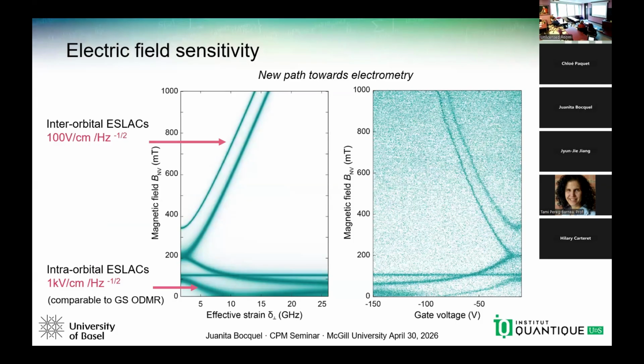I think, but when applying large electric fields, other problems would arise for some of the applications that I mentioned earlier. What we found more interesting, actually, is that those features are very similar to the magnetic resonance transition that I introduced at the beginning. In particular, those ones are very sensitive to electric field, in a way that might actually open a path towards electrometry, which is not really common with NV centers, which is mostly about magnetometry. It's also possible with those features, but in the end, one is not really gaining any sensitivity compared to just looking at the Stark shift from the ground state.